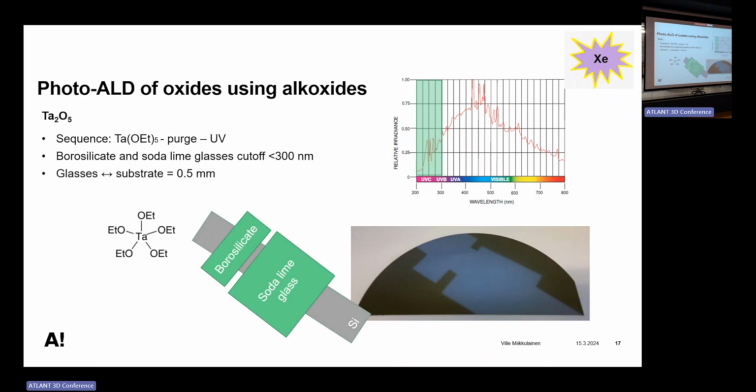So if there was any photothermal effect, it would arrive from this part of the spectrum too, and we would only minimally decrease the growth rate with this experiment. But since it kills it completely, it must be this part of the spectrum that is at least mostly responsible for the photoreactions in the system.